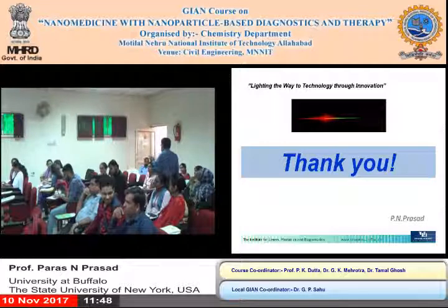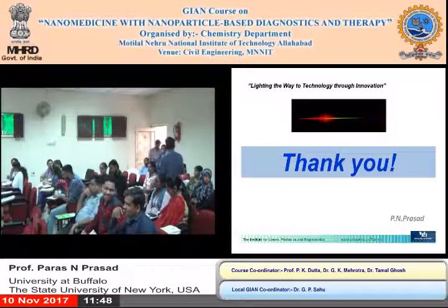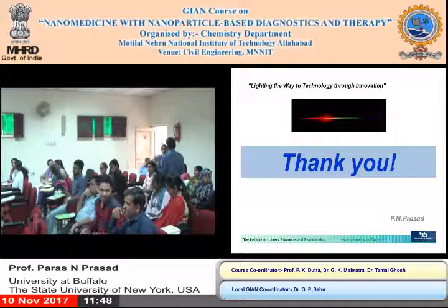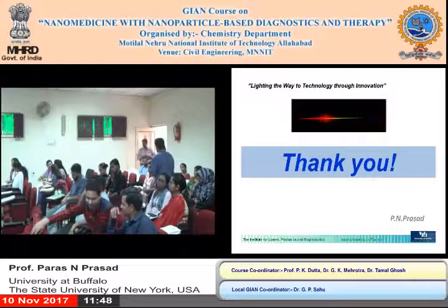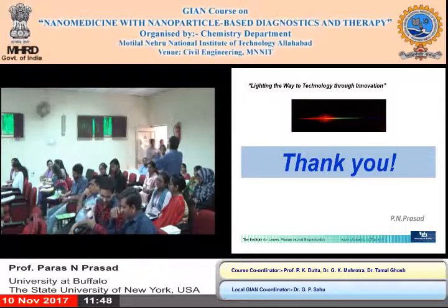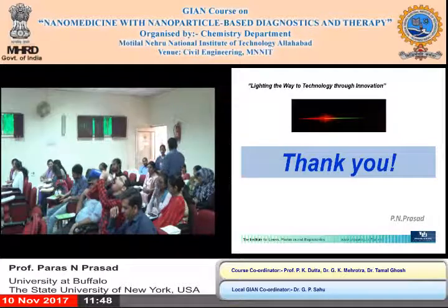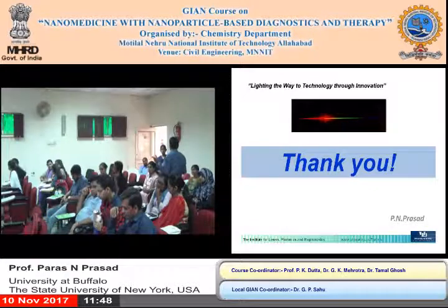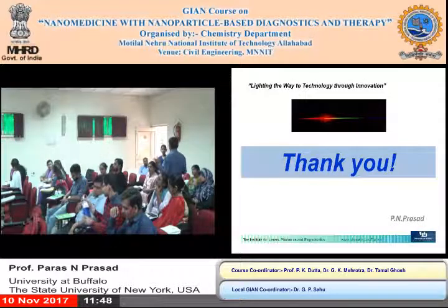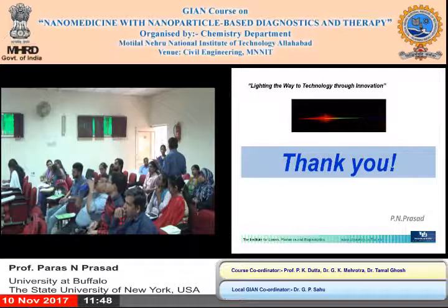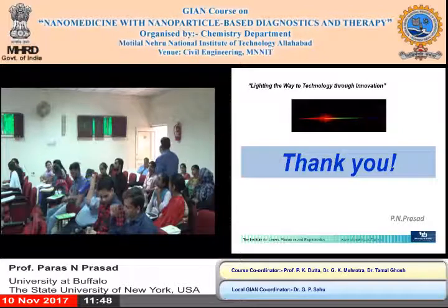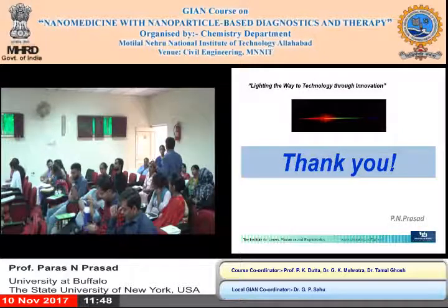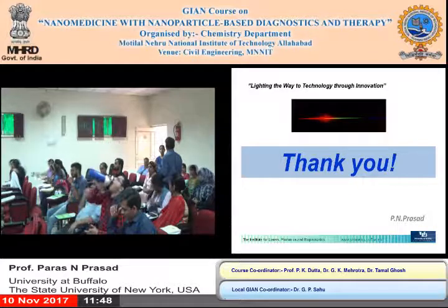Okay? And so currently most of the photodynamic therapy is done with a continuous wave laser, not a pulse laser. You don't need to do that. But if you are doing upconversion, where you convert low energy light to higher energy, going up, and then do the therapy, if you use nanoparticles with a rare earth, you can still use a continuous wave laser or low power laser. But if you use an organic dye with virtual state two-photon absorption, then you need a pulse laser. Then you need picosecond or femtosecond lasers, which are expensive.